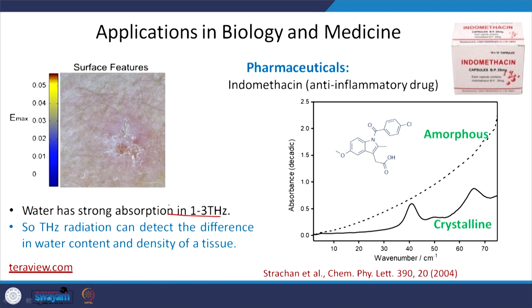Another example is detecting pharmaceuticals. In the pharmaceutical industry, the amorphous and crystalline structures of a drug such as indomethacin, an anti-inflammatory drug, have different absorbance in the terahertz region. So if you are making a tablet and you want to confirm whether it is crystalline or amorphous, terahertz tells you not just the chemical composition but also the crystallinity — which matters because the same compound in different phases has different absorption spectra and may be suitable or unsuitable for use.